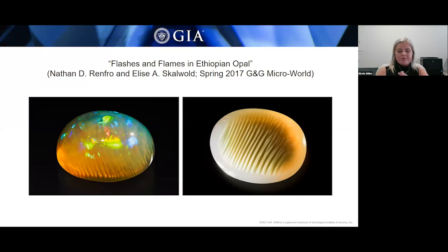Opal mined from Ethiopia is known to produce materials with vibrant plays of color, as well as some interesting inclusions every now and then. Pictured here, we have a 2.68 carat oval cabochon opal, and it had a combination of play of color and chatoyancy. The image on your left is the cabochon face up, where one can directly see that play of color. And next to it is an image of that cabochon from the base up, and that depicts that waved structure that produced a sheen-like chatoyancy.